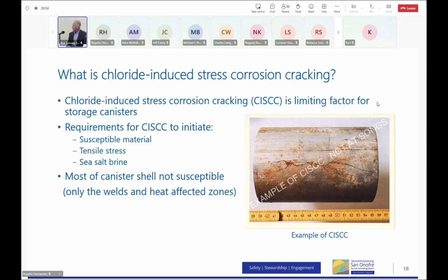Terry, could I ask a quick question, please? Yeah. What's the difference between this and just plain rust? Well, this isn't just plain rust. You don't get much just plain rust on stainless steel. You might get a surface layer of oxide, and we do see that on our 304 stainless in the field. But stress corrosion cracking, the difference is that it has tensile stresses causing cracking, and those cracks go subsurface. They'll go clear through the pipe. Rust, on the other hand, would just have to work its way through the pipe over the years. Okay, thank you very much.